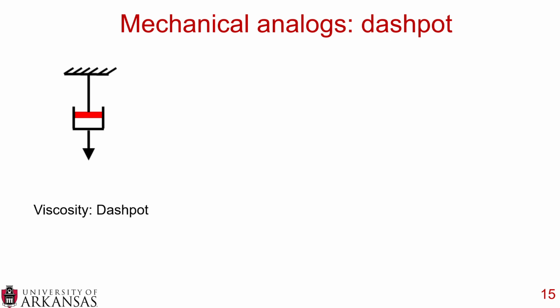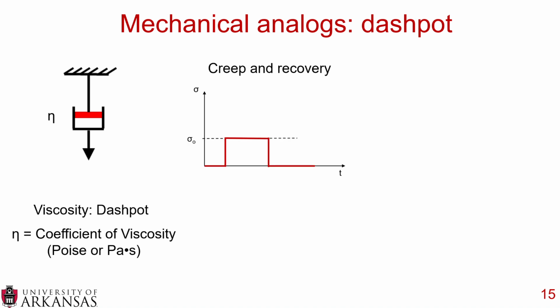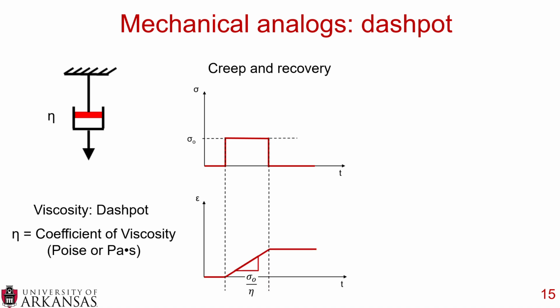The next most common is a dashpot mechanical analog, and this measures the viscosity of a material. And this is represented by eta, and eta is the coefficient of viscosity, and that's either measured in poise or Pascal seconds. So again, let's pretend we do a creep and recovery test. You put some sort of constant stress on, and you apply that for a certain amount of time, and then you release it back to zero. Well, the strain looks a little different.